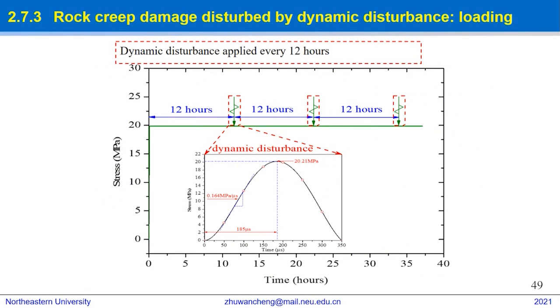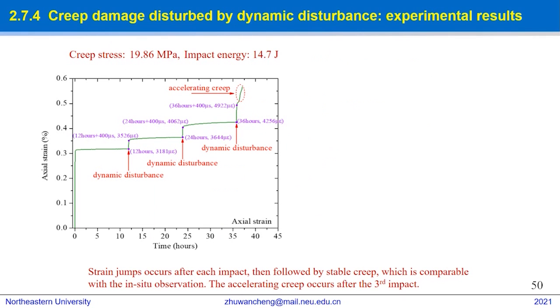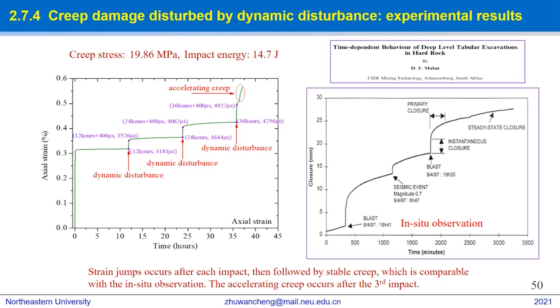As shown in this figure, the first dynamic disturbance was performed after 12 hours and the remaining dynamic disturbances were performed at every 12 hours until the specimen failed. Strain jumps occur after each impact, then followed by stable creep, which is comparable with the in-situ observation. The accelerating creep occurs after the third impact in this experiment.